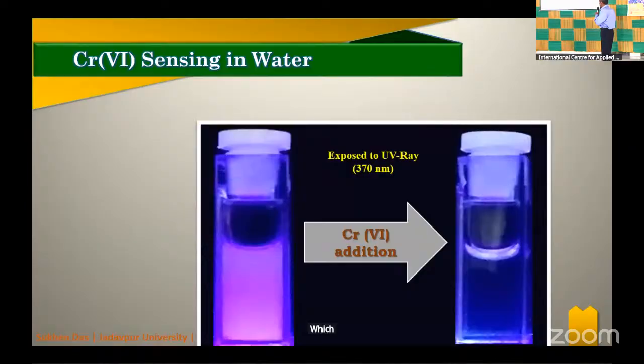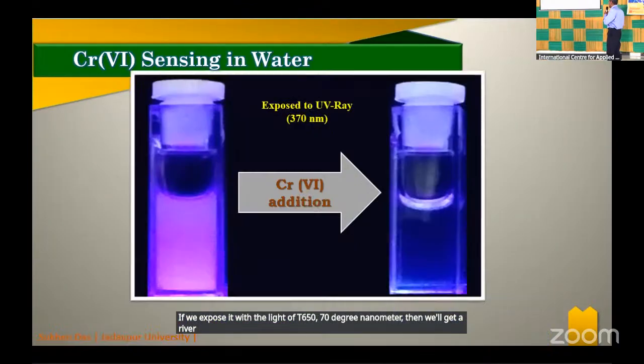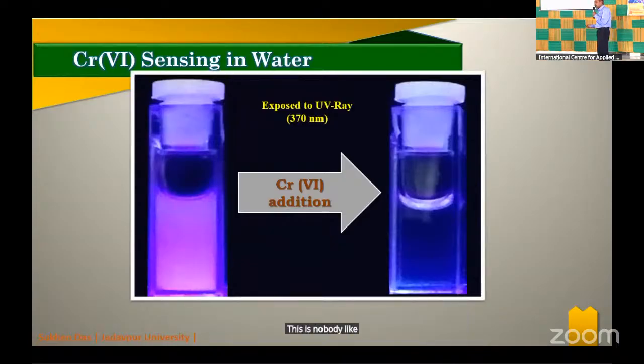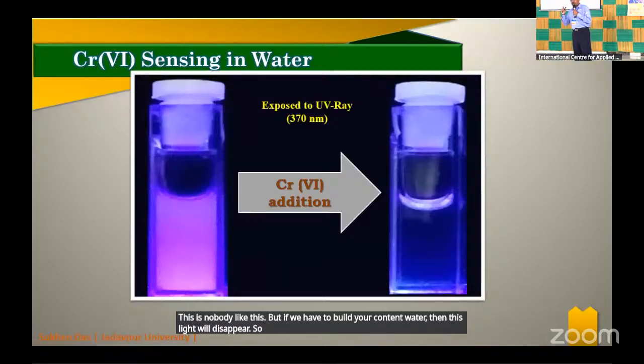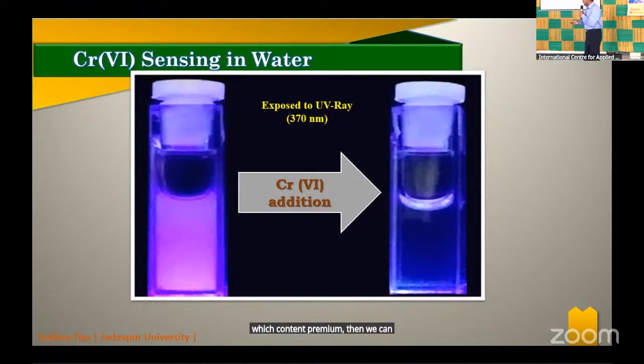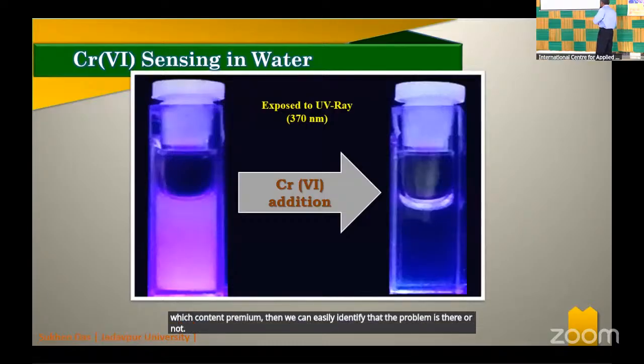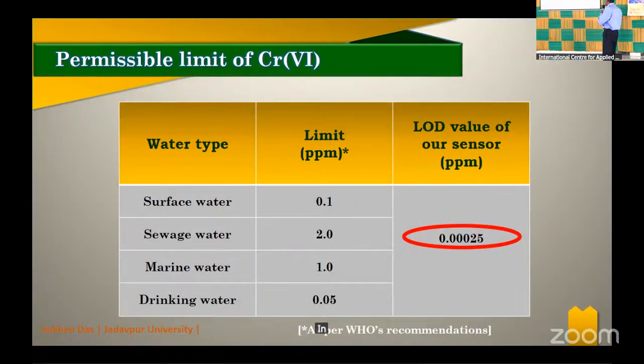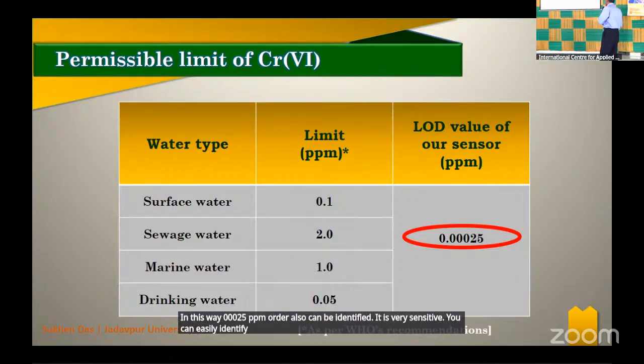Actually, if we expose it with light of 370 nanometer, then we'll get a reddish fluorescence property like this. But if we add chromium or chromium-containing water, then this light will disappear. So if we can find a device where this type of fluorescence property is there, and we put one drop of water which contains chromium, then we can easily identify whether chromium is there or not. In this way, even the 0.00025 ppm order can be identified. It is very sensitive.